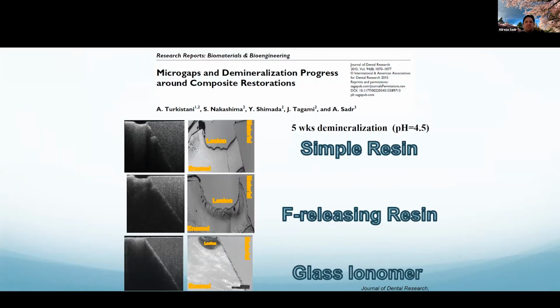So when we look at the effect or potential effect of fluoride release, and that's basically what we want to focus on here when we talk about sealants, in artificial caries models that we'll look at, you get secondary caries. I don't know if it's secondary caries, maybe this is primary caries. We had this discussion with Journal of Dental Research reviewers, and we finally said caries forming around a restoration. It's not really a sealant, but sealants are very similar if you have enamel there. And you find a much less incidence of formation of lesion in this particular acid-based model, in vitro model, with application of a glass ionomer.